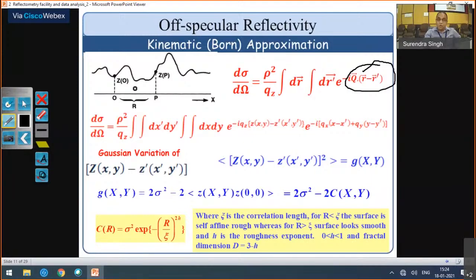They follow the Gaussian roughness, Gaussian variations. If this parameter z minus z dash follows the Gaussian parameters, we can redefine these whole things like g(xy), 2 sigma square minus 2. Here this sigma is the actual height variation.